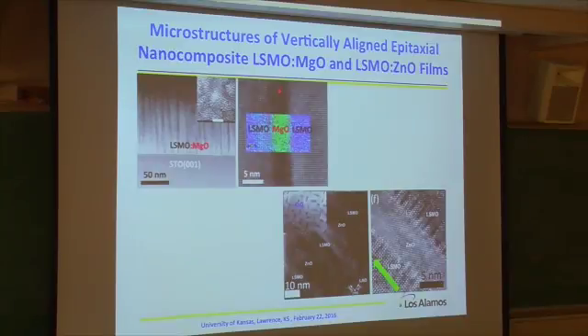Same thing over here, for example, zinc oxide and LSMO. The zinc oxide is also the second phase. Look at this cross-sectional, and you see it's a very, very sharp interface. You can really grow very, very high quality material. And then you can use this phase to control the LSMO property as well. And also, actually, vice versa.